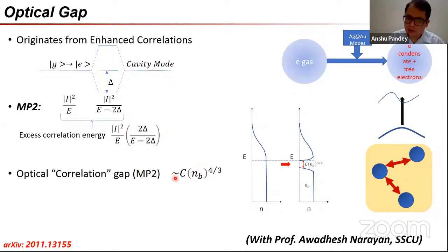Okay, there is an optical correlation gap which comes about, which is of the order of the number of bound electrons raised to 4/3. This can be reasonably estimated using, say, an MP2 type approximation. So this provides the impetus for the system to actually localize.